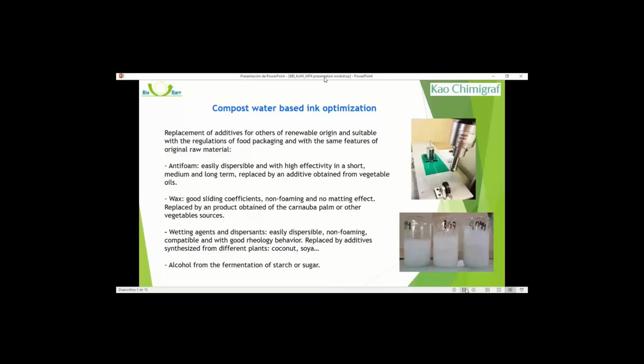We also checked their effectiveness in the short, medium, and long term. It means the volume of foam generated in the ink and the time needed to remove it. Finally, we also checked their interactions with the slip and gloss of the ink. With other substances, waxes, wetting agents, dispersants, a similar process was carried out. At the end of all this work, we selected defoamers based on vegetal oil, waxes of the Carnauba palm, and some surfactants obtained from coconut, soya, or other plants.